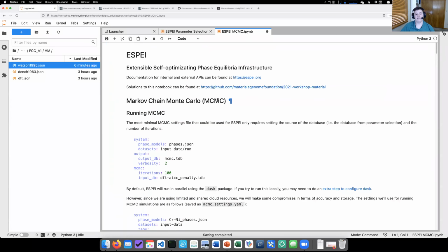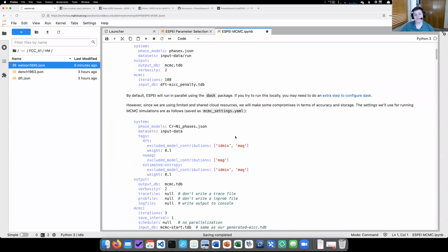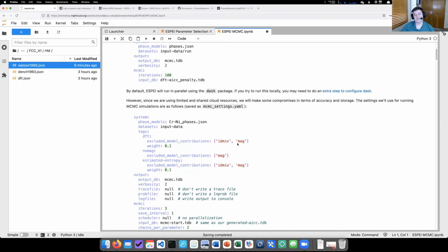And like I said, the way that I do DFT, even with the spin polarization, you aren't really capturing the CALPHAD magnetic parameters, which is really modeling the magnetic entropy. So the spin polarization doesn't give you that part. And that's where I'm struggling. It's not only the entropy, you also have a contribution to the enthalpy. Yeah. I think of DFT more in terms of enthalpy rather than entropy.